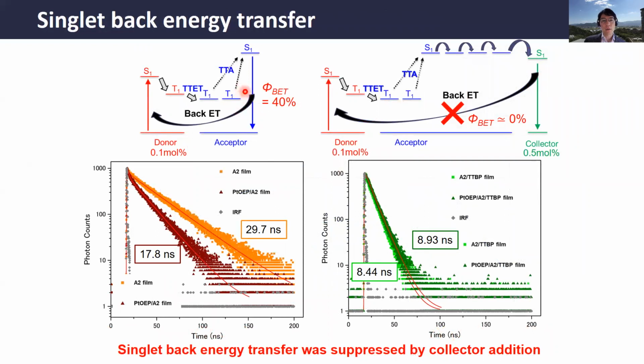But more importantly, we observed the suppression of singlet back energy transfer by the collector. In the two-component donor-acceptor system, we observe 40% back energy transfer, but by adding the collector, such back energy transfer almost did not happen. This is because the donor and the collector are at low concentration, so their average distance is farther than the FRET radius, so that back energy transfer can be almost avoided. Thanks to this suppression of back energy transfer and also the improved fluorescence quantum yield, we could observe higher upconversion efficiency.